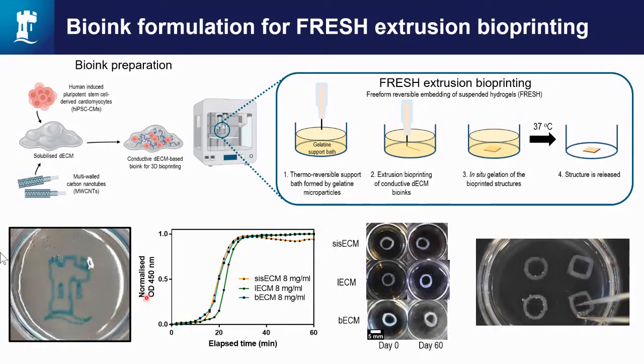As you can see here in this example, using this method and these inks, we can print relatively complex structures. We've also studied the kinetics of the gelation to understand when our materials are fully gelated and when we are able to remove the gelatin. So as you can see here, after 20 to 30 minutes, the structures are fully gelated and we are able to remove the gelatin bath.